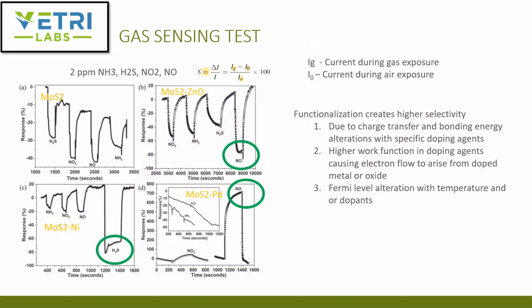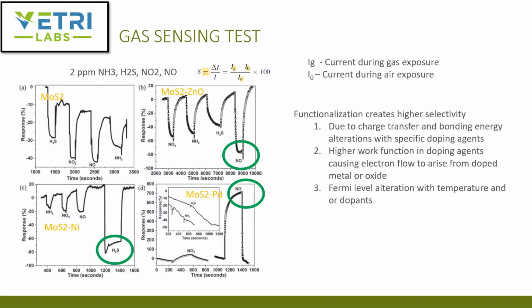Okay. So the test was, once the device was fabricated and the baseline curves were taken, they started the challenge gas test, which is, in this case, there's a lot of charts here I'll walk through. 2 ppm of ammonia, 2 ppm of hydrogen sulfide, 2 ppm of nitric and nitrous oxides were the challenge gases. And the goal is obviously to have at least one of them and to be able to dial in a particular level of sensitivity to these gases.